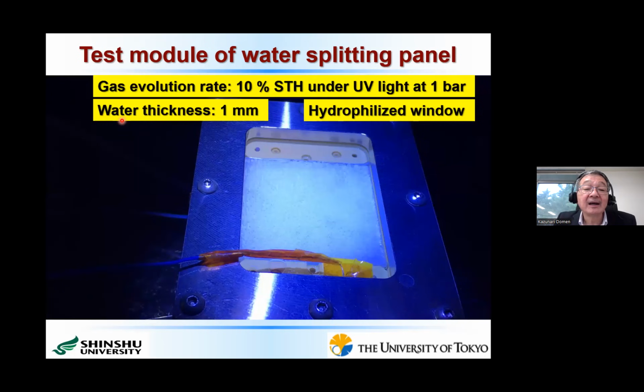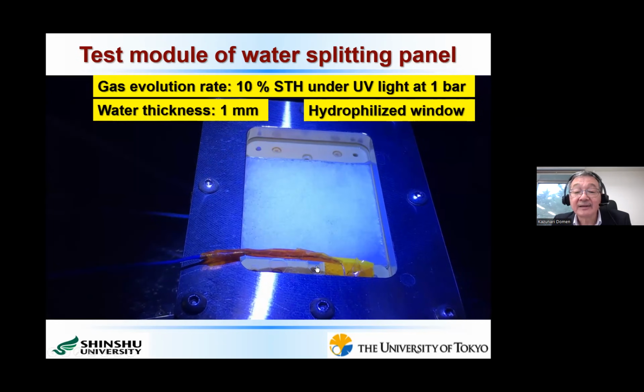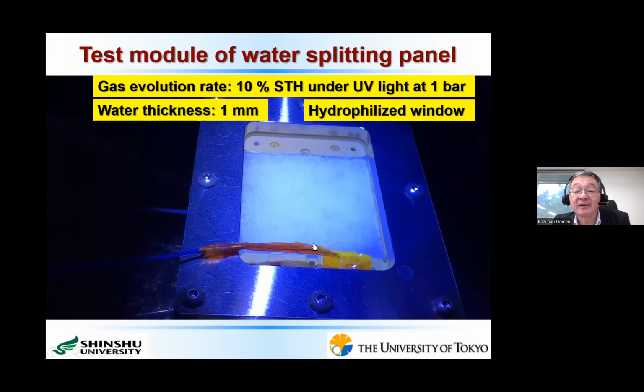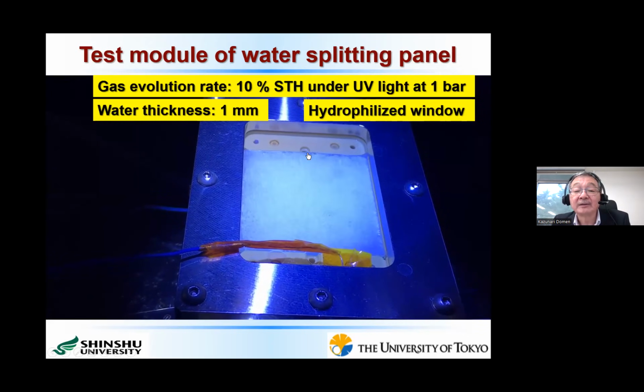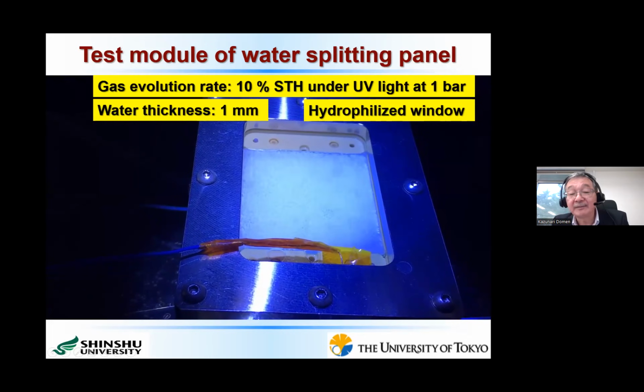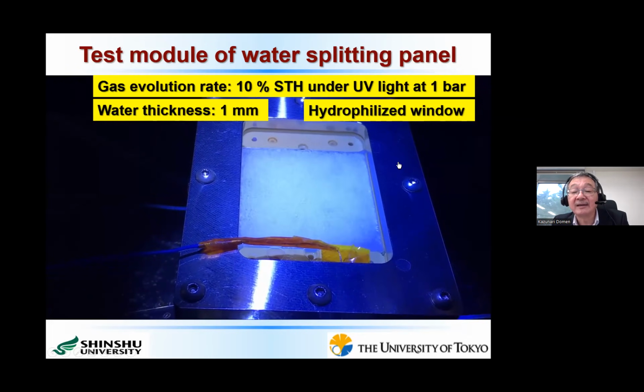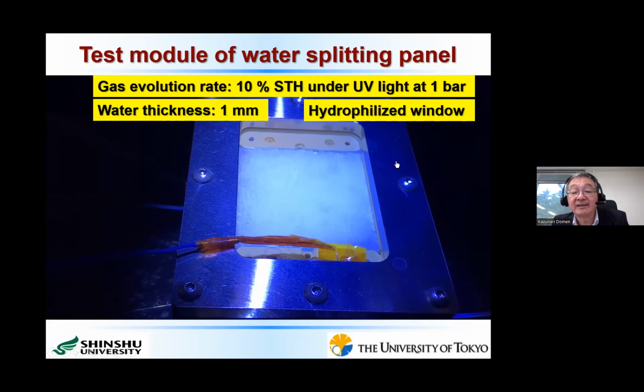In this case, we use a 1 millimeter thickness of water layer, and we irradiate a strong UV light to achieve about 10% solar to hydrogen energy conversion, corresponding to the 10% STH bubble formation rate. So you see that the small bubbles are going up very quickly and go outside from the top of this small hole. That means that even at the rate of gas evolution of 10% STH, there is no problem for this kind of water splitting panel.